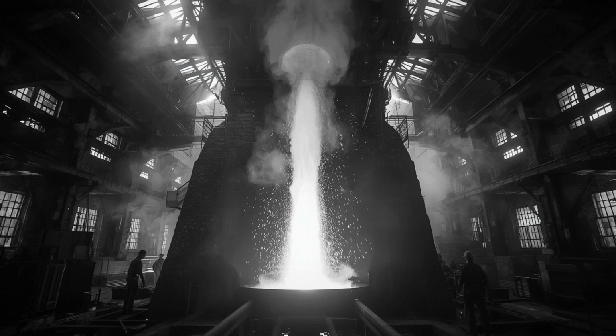It takes 3 days to bank the furnace, let the charge burn down, and cool the interior enough for entry. When the crew finally goes inside with lanterns and plumb bobs, they find everything structurally sound. No blockages, no collapses, no warped plates or shifted tires. The geometry is correct. But the evidence of division is everywhere. The brick on the left side is coated with thick carbon deposits, the surface almost glossy. The right side is etched and roughened, the mortar joints recessed from erosion. A vertical line separates the two zones, running from the hearth to the throat, perfectly straight, as if drawn with a rule.